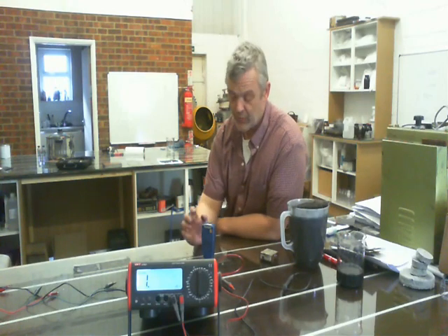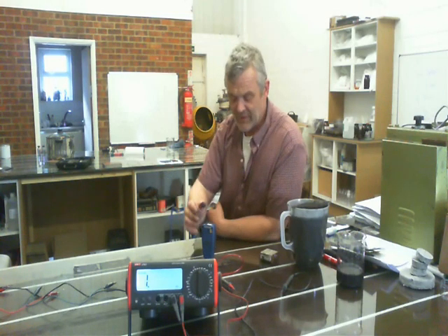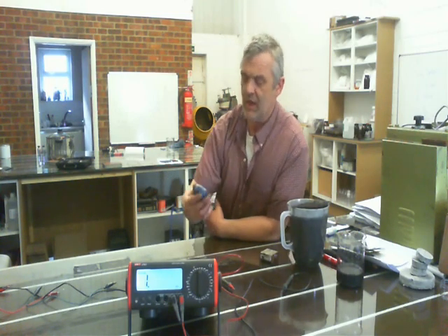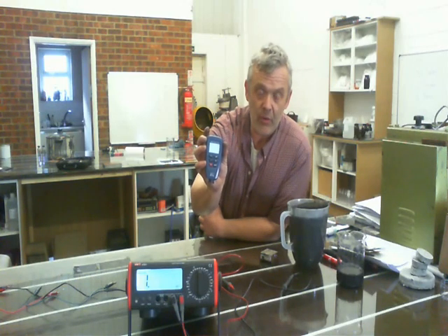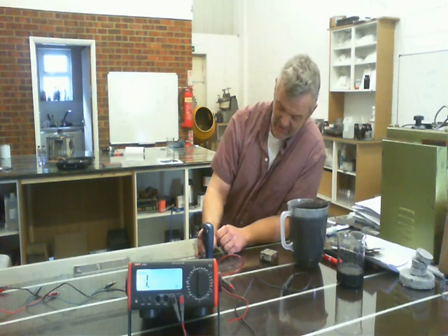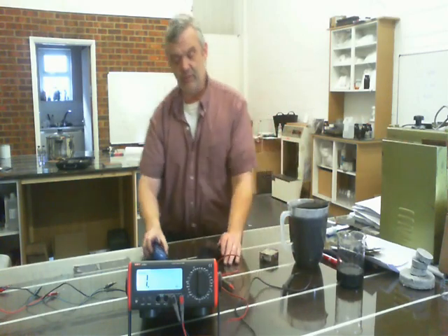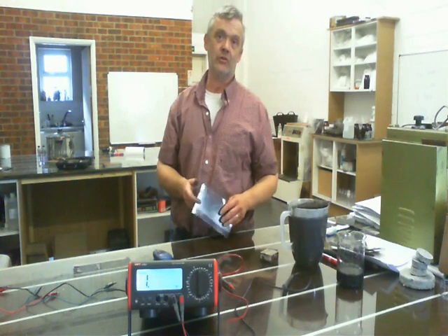What I've got here is a paint film thickness meter, meant for measuring the thickness of paint films on cards. Now it won't go less than one micron, so there's a fair degree of error, but it will certainly give us an idea of the resistance we're getting. First we measure the thickness of the film and the plastic together, because the ink lays on top of the plastic — and we get 81 microns. Then we move it and measure just the plastic, which gives us 78 microns. So the paint film is 3 microns thick.